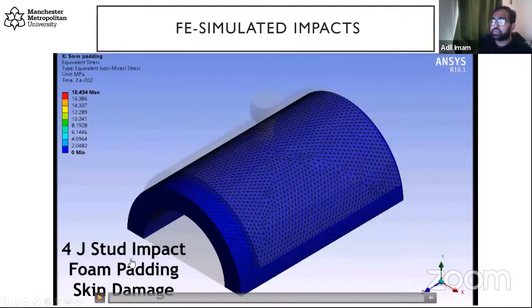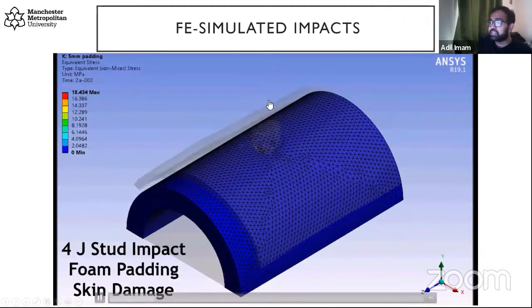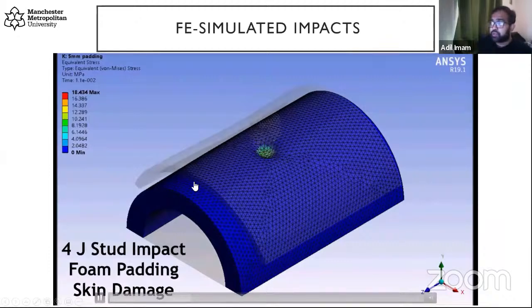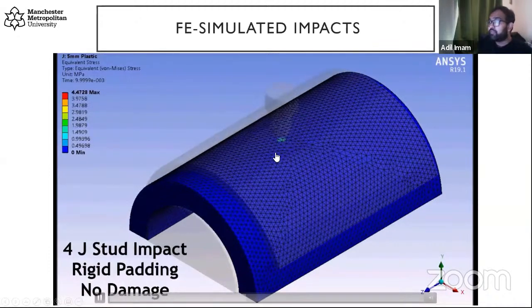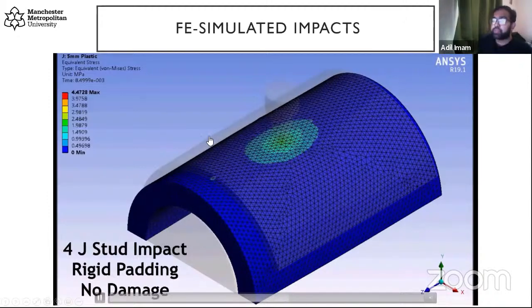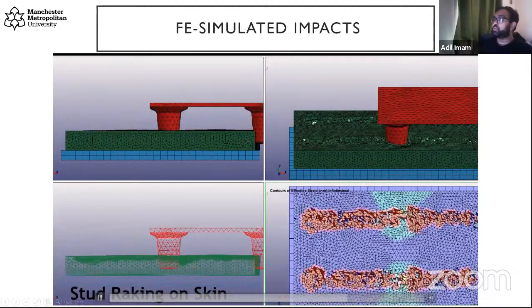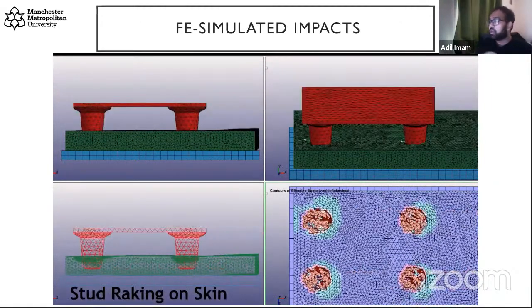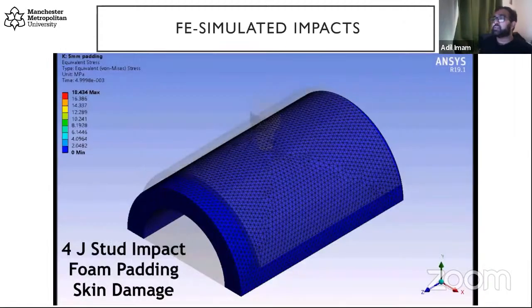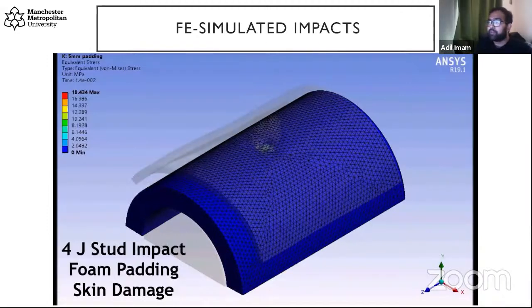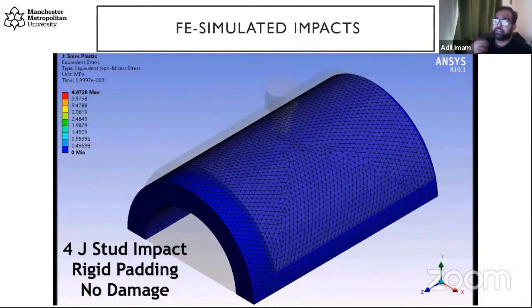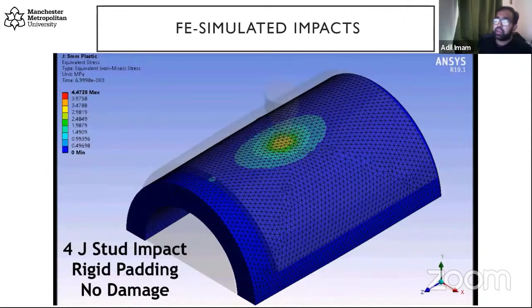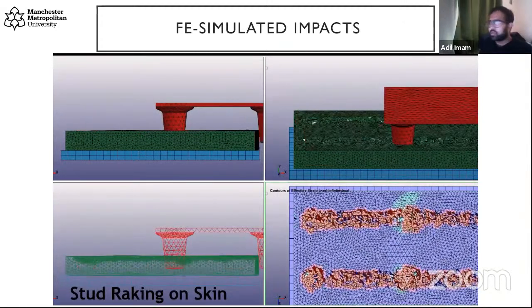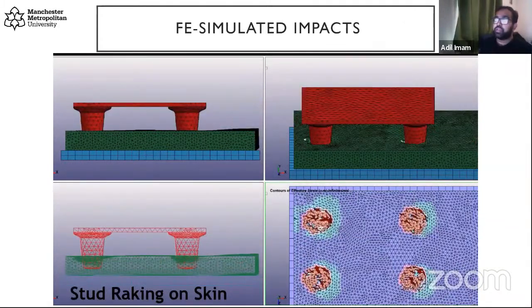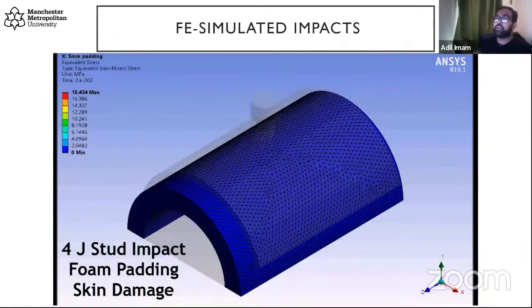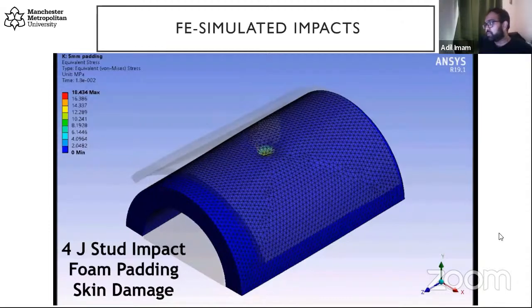So let's say we can introduce foam paddings of different properties and see how the skin would tear if we use the soft, or if we use the stiff or a rigid padding, how the force dissipates. Not only that, we were able to simulate different impacts. So, someone stamping on a player and pulling the leg back would result in a skin tear. So the ability of FE, again, is once you've validated the model, you can mimic different scenarios. And using this model, you can test out different scenarios of impact or different padding, which might be soft or rigid, and figure out if this should be allowed or this should be regulated or not.